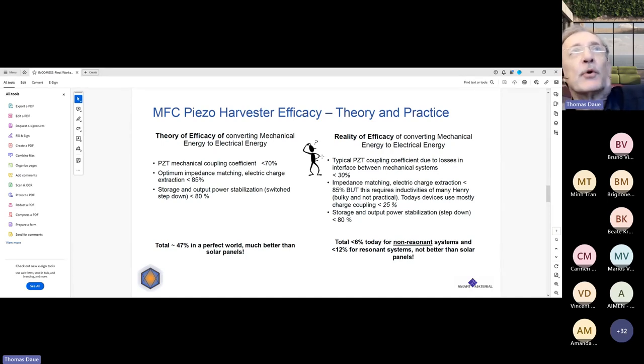Why is that? So the theory for mechanical energy to electrical energy is: PZT has a mechanical coupling coefficient of less than 70%, so it's pretty high. If you have an optimum impedance matching, you can have an electric charge extraction of 85%, and storage and output power stabilization with a step down approach can yield 80%. So totally, in theory, you can get 47% efficacy, which is much better than solar panels.